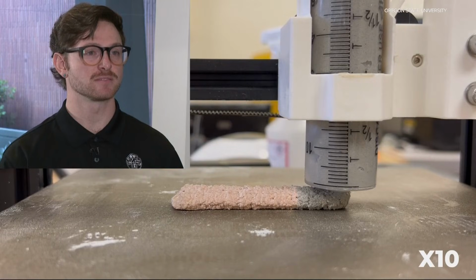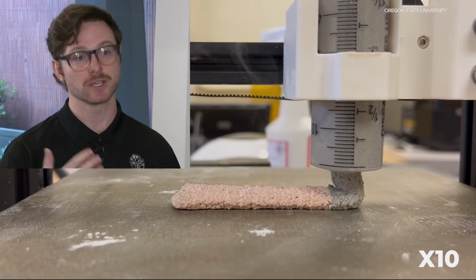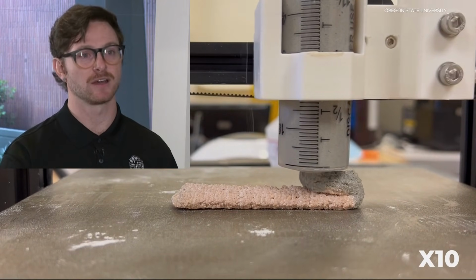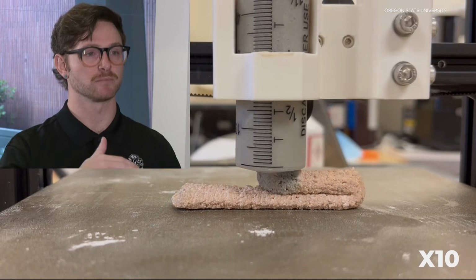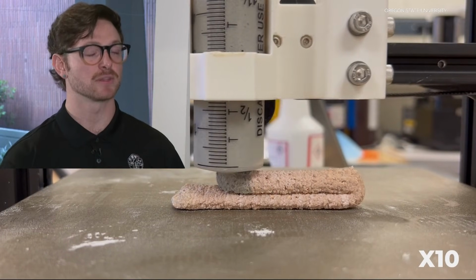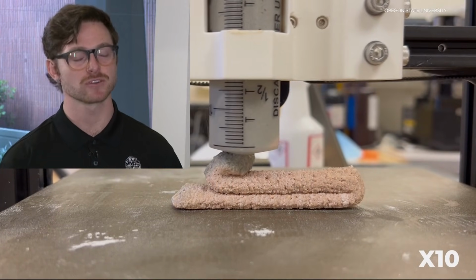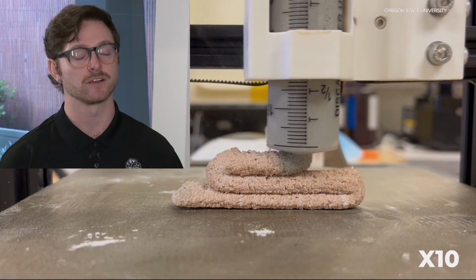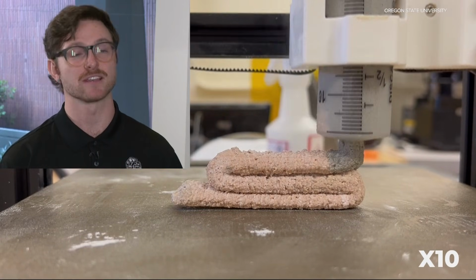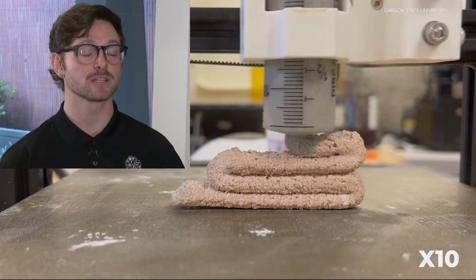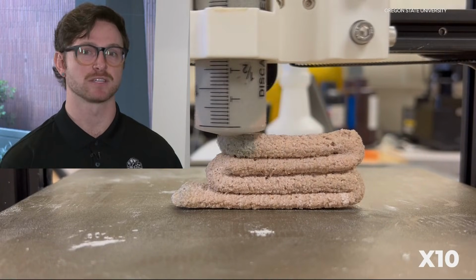We found that these materials can achieve about 3 megapascals of strength immediately after 3D printing, which means you can print many layers one on top of the other. But then after only 3 days, we can get structural strength of concrete required for buildings and infrastructure, around 17 to 20 megapascals. Typically with cement-based concrete, this takes up to a month.